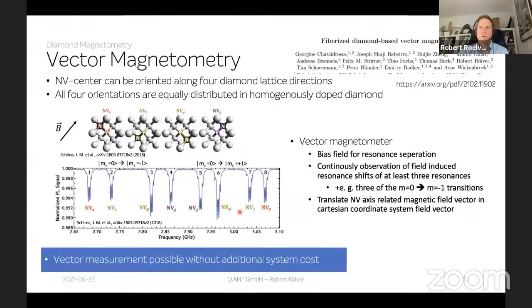And if you look at the ODMR spectra of such a homogeneously doped diamond, then you have 4 pairs of energy splittings, because the magnetic field projects differently onto the 4 different axes. So from every axis you see 1 pair of resonances. So you have these 8 resonances. And from the changing of the resonance frequency of all these, if you observe them simultaneously, you can calculate the magnetic field vector. And for this, you also need, of course, a bias magnetic field that makes all the 8 resonances visible in your spectrum.